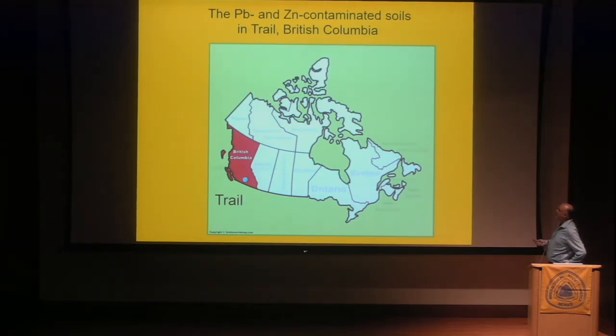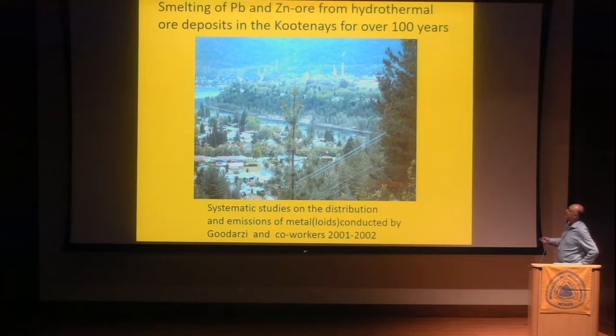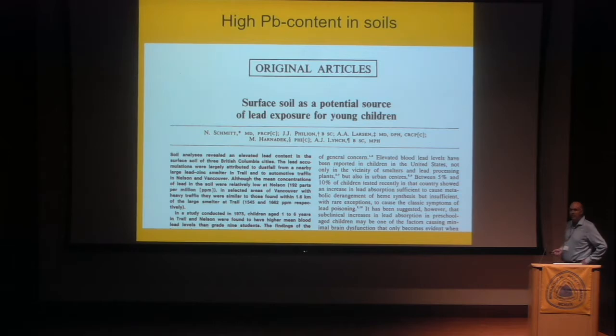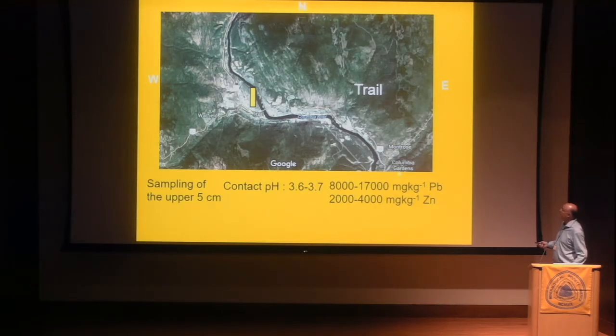So one of the case studies, the most interesting one, we did in Trail in British Columbia, that is down here. Trail sits on the Columbia River, and smelting processes at a local smelter for lead-zinc ore from the Kootenays have occurred for over 100 years. The lead content in this local soil was at one point so high that they actually had to test the children for the amount of lead in their blood. And so we sampled along the Columbia River here. Here's a smelter, and we sampled around here.